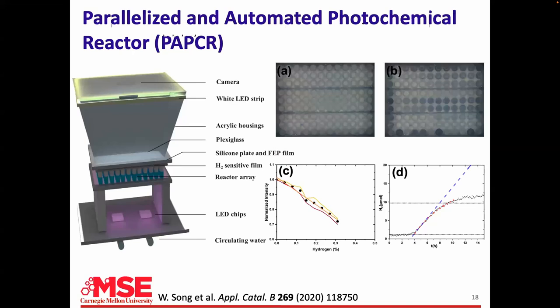Every new method has advantages and disadvantages. The advantage here is that in two days, a student can set up and run this experiment and characterize 100 catalysts — the hardest part is physically massing out milligram quantities into 100 little vials. We can also assess reliability by putting five of the same catalyst in, and we put five standards — platinized P25, the photochemical standard — in every run, so we can benchmark from run to run and get uncertainties on results.